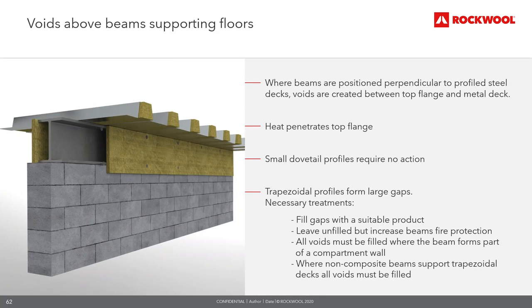Voids above beams supporting floors. When do we actually need to fill those voids above composite and non-composite beams? There are preformed blocks available to fill the voids between the deck and the top flange of the beam. Any non-combustible material with a proven fire stopping ability can be used. Where beams are positioned perpendicular to a profile steel deck, voids can be created between the top flange and the metal deck. Generally, small dovetail profiles will require no action, whereas the larger trapezoidal openings may need treatment.